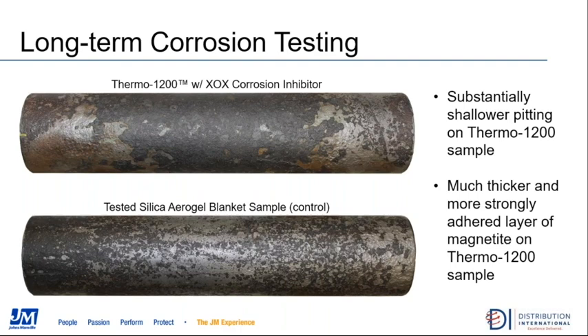I'm not going to get into great detail, but the whole point on this test is, with corrosion, what you're looking for is how deep the pit is, because that's reducing the wall thickness of the pipe. And the result is Thermo 1200 resulted in substantially shallower pitting than, in this case, silica aerogel, which we tested against. So that's the key. That's what everybody's looking for. That's what all the end users are interested in, the depth of the pit. So that's the big takeaway from this slide.